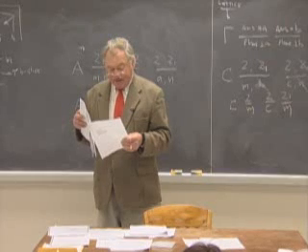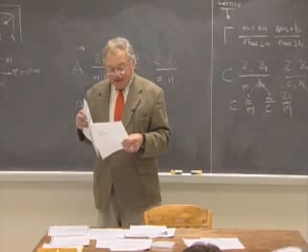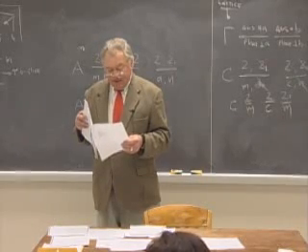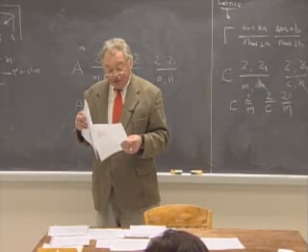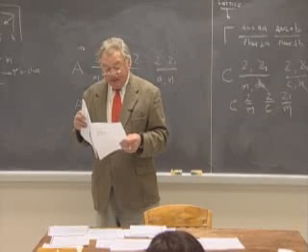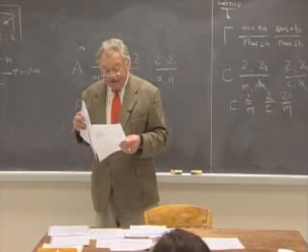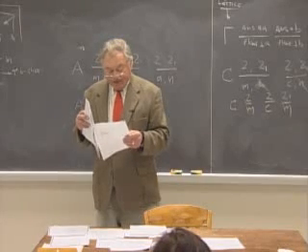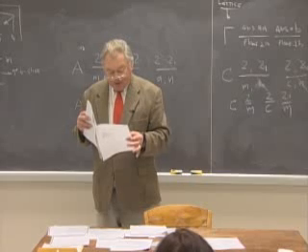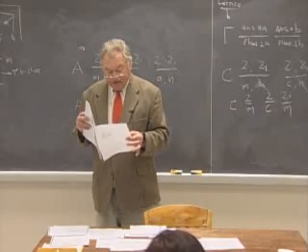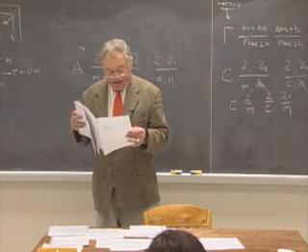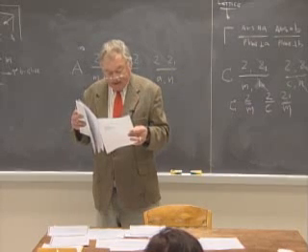They've done some very useful things. They have specified the asymmetric unit within which you need specify coordinates of atoms. And here they say that you have to tell what's in the range x equals 0 to x equals a half, y equals 0 to y equals a half, and z less than or equal to a half, but greater than or equal to 0. Then they give a representative set of symmetry operations which generate all of the atoms within the unit cell. The symmetry operations are not independent, but they list 16 symmetry elements.